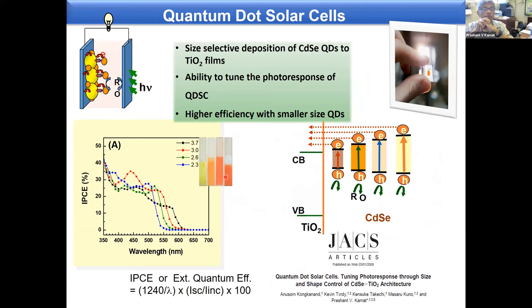Quantum dot solar cells. From that, we moved on to the quantum dot solar cells. For about 10 years or so, until the perovskite came in, this was one of the hot fields in the early millennium, between 2000 and 2012. This was one of our first studies where we showed that you can deposit these size quantized semiconductors on electrode surfaces, and they show this same kind of photo response. And again, the higher efficiency you see with the smaller size comes from the larger band gap.